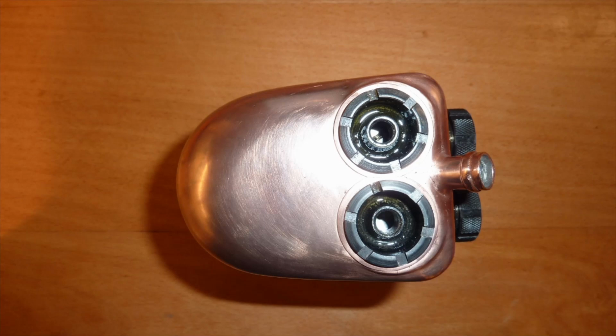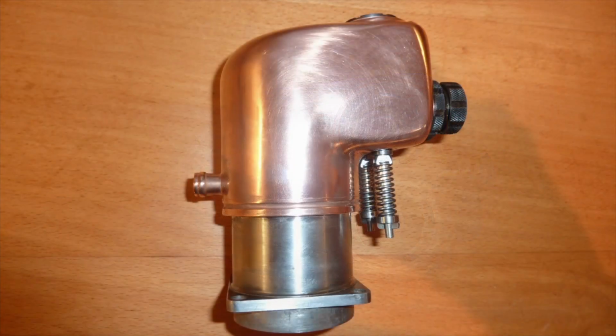I got some idea of the thickness of the plating from my detailed record of weight. The change in weight during plating could be used to calculate the mean thickness, which was a guide but told nothing about the unavoidable variations. Generally, I knew that sharply curved areas like corners and fillets around the stub pipes would get a heavier deposit relative to broad, flatter areas, and this seemed like no bad thing.